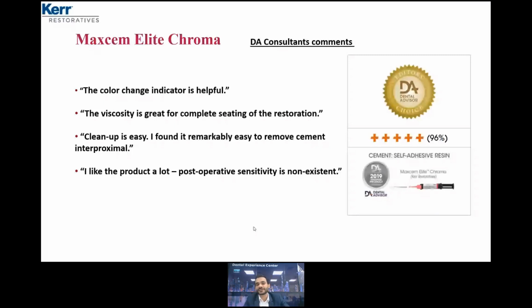And at this point it's important, because if we talk about the chemistry, why do we say we have low or no post-operative sensitivity with Maxcem Elite Chroma? Because at the beginning, Maxcem Elite Chroma is highly acidic, around 2.2 to 2.4 pH, because we first needed high etching power for the enamel and dentine. But within 4 hours, it reaches almost 6.5, almost 7 pH, which means it very quickly reaches the neutral phase. So we don't have post-operative sensitivity.